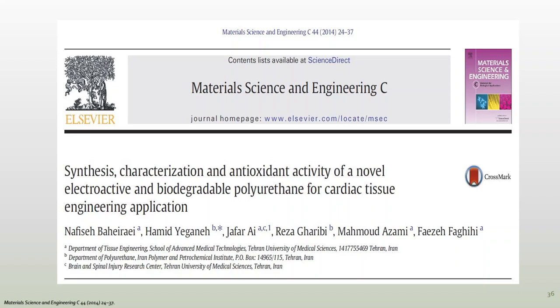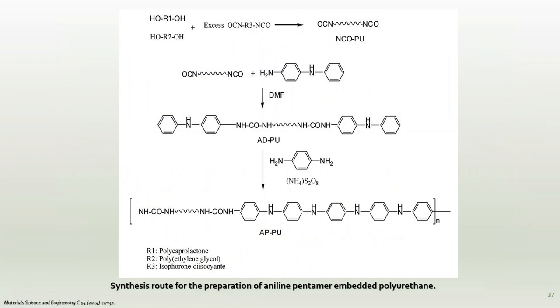In another study, we made an electroactive polyurethane for cardiac tissue engineering. The purpose was to fabricate a novel conductive polyurethane containing aniline pentamer moieties and its blend with polycaprolactone. Our data showed that the electrical conductive substrates prepared in our lab are non-toxic and could support cell proliferation and attachment combined with antioxidant properties.